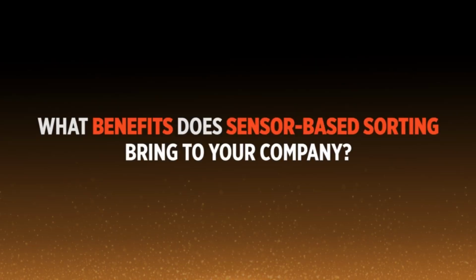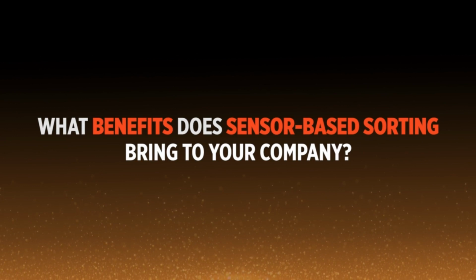We see an increase in consumption as new buildings for both residential and commercial use take advantage of the thermal, UV and aesthetic benefits that aluminium gives to windows, doors, and curtain walling as well. Sensor-based sorting has changed the way that we are able to process material. Historically, we've processed pre-consumer fenestration window scrap extrusions. So we've been able to separate the polyamide strip away from the aluminium, which has been hugely advantageous to our business. So much so we're probably processing around 10,000 tons a year of this material to the fenestration sector.